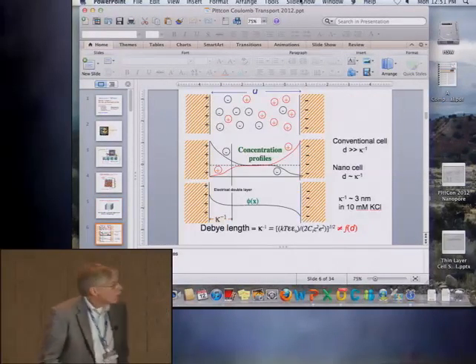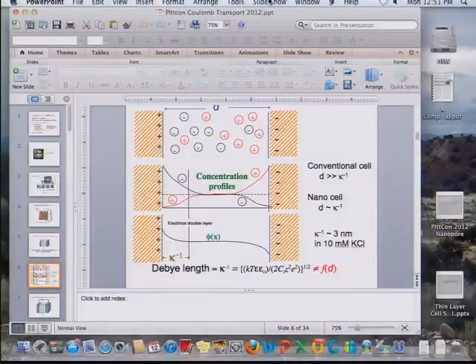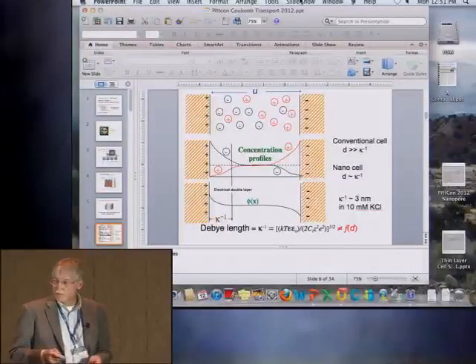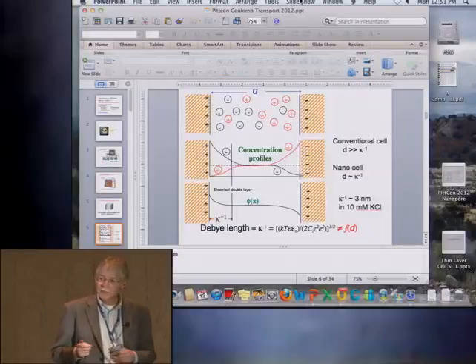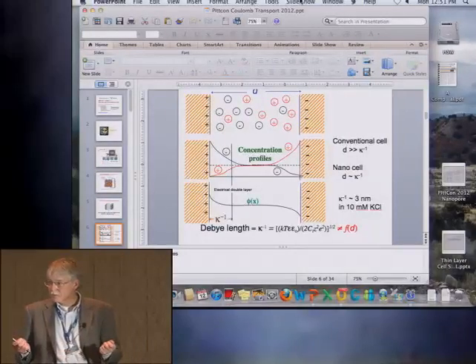What will happen? The physics is very, very simple. We're just worried, initially at least, with the overlap of the electrical double layers between the 2 electrodes. So if I have a cell thickness D up here, I'm going to have an electrical double layer at both interfaces, or the concentration profiles and the potential profile. And the thickness of these electrical double layers is characterized by the Debye length. The Debye length is not a function of the thickness of the cell. So you have 2 characteristic length scales that you have to compare here. The thickness of the electrical double layer relative to the thickness of the cell.